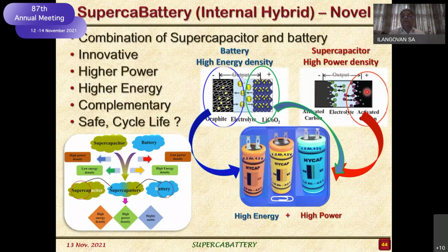Why am I using only the positive electrode? Because the negative electrode of the lithium ion and the negative electrode of the supercapacitor, voltage wise there is no matching. If you look here, this is supercapacitor, high power, low energy, but battery, low power, high energy, which I was telling. But there are a host of other conceptual matchings to take place. That is, I cannot match the anode of lithium ion and the anode of the supercapacitor. At the same time, there is a crux in matching the cathode as well as the cathode of the supercapacitor.